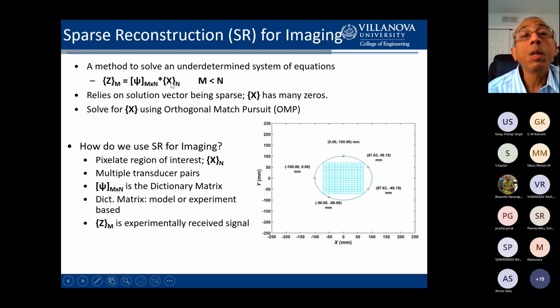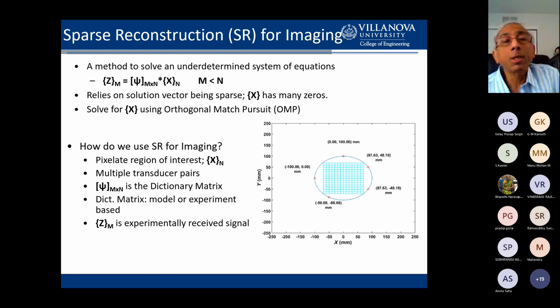This is your unknown defect location vector. You're trying to find it. And this is your collected signal. And this X vector is very sparse, very few non-zeros in it, very few defects in your structure. So then you can attack it with this orthogonal match pursuit algorithm and solve for the locations of the defects. So that's fundamentally, in a broad sense, how we adapt sparse reconstruction, which is a mathematical concept, and apply it to this particular application of imaging using guided waves.